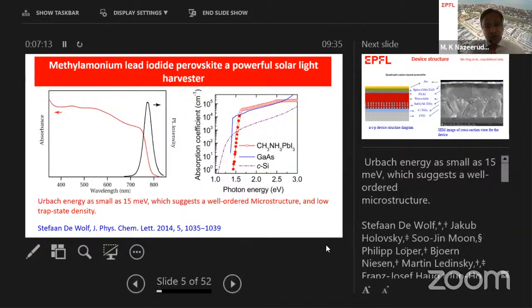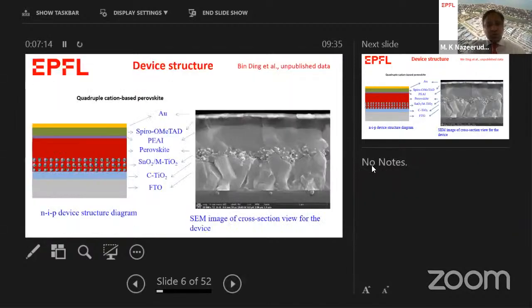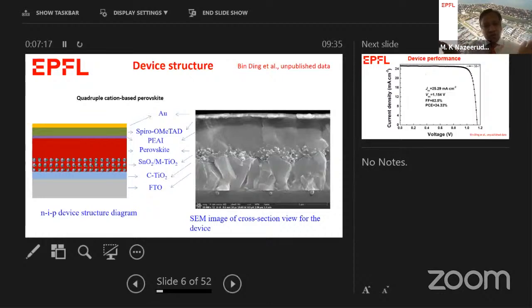So with this, I would like to go to the next slide to show the perovskite solar cell design configuration. In the perovskite solar cell community, there are two types of perovskite solar cells. One is called NIP, another is called PIN. Here we are describing the NIP structure. The NIP structure typically has a conducting glass, and we deposit a compact layer of TiO2, a very small layer of TiO2. Then we have mixed tin oxide and mesoporous TiO2 mixed oxide layers on top of FTO glass, followed by the perovskite deposition, and a very thin layer of two-dimensional perovskite, shown here, phenylethylammonium iodide as a two-dimensional perovskite cation, and hole transporting material.